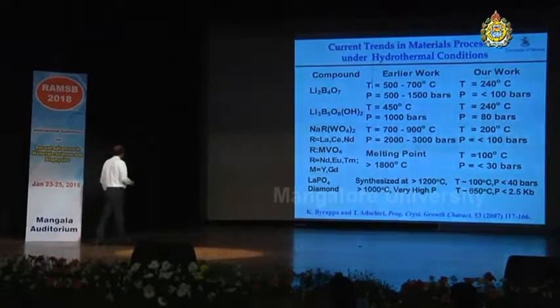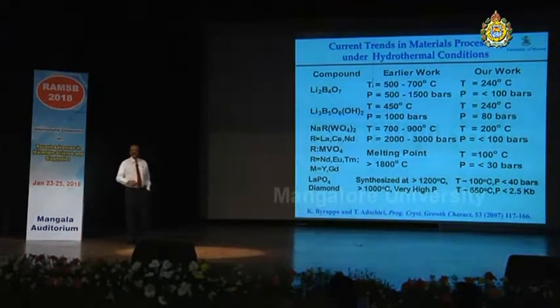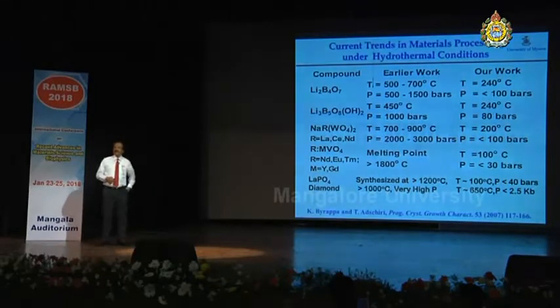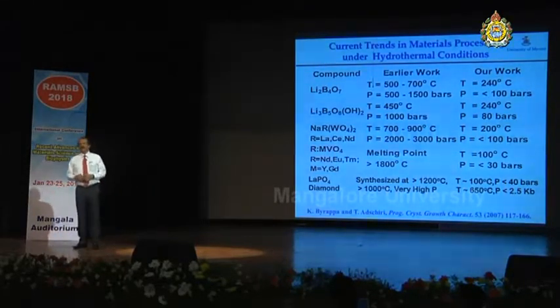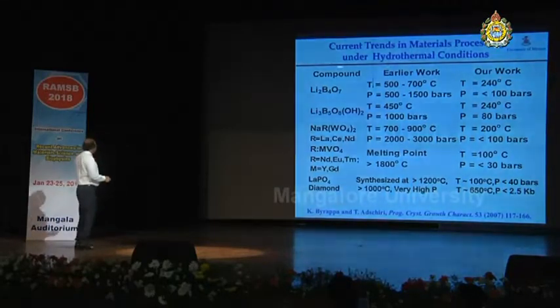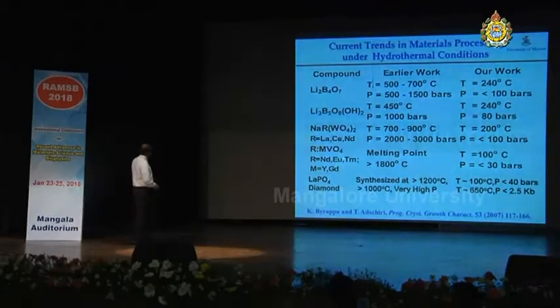Well, this wave graph shows the current trends in materials processing under hydrothermal conditions. In the earlier days, as I mentioned, hydrothermal referred to very high temperature and high pressure processes. I have listed some of the compounds which we have worked on extensively, and these are the experimental conditions used by the earlier workers. This third column shows the experimental conditions we have used, and you can see a very significant drop in temperature, and accordingly the pressure, less than about 30 bars in this case, and here less than 100 bars. That's a great contribution to the field of hydrothermal technology.